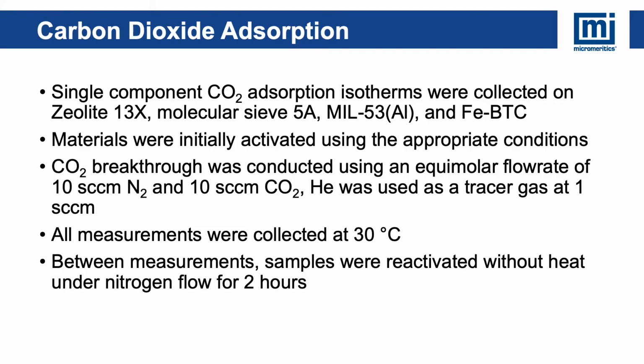So the first experiment I wanted to talk about is carbon dioxide adsorption. In this experiment, I collected single component CO2 adsorption isotherms on zeolite 13X, molecular sieve 5A, MIL-53 aluminum, and iron BTC. Materials were initially activated using the appropriate conditions for all the materials as were found in the literature. CO2 breakthrough was conducted using an equal molar flow rate of 10 SCCM nitrogen, 10 SCCM CO2, as well as using a small flow rate of helium as a tracer gas.